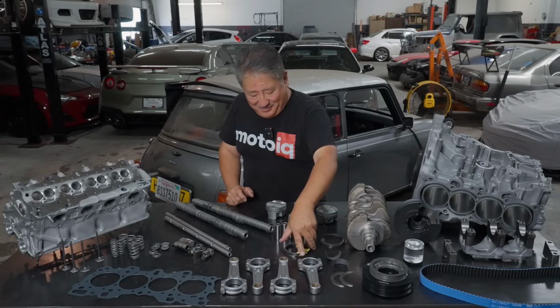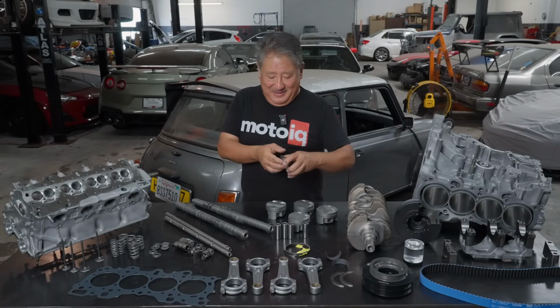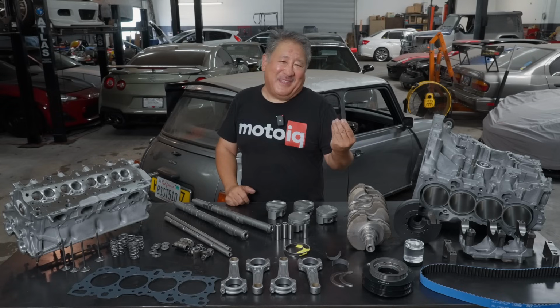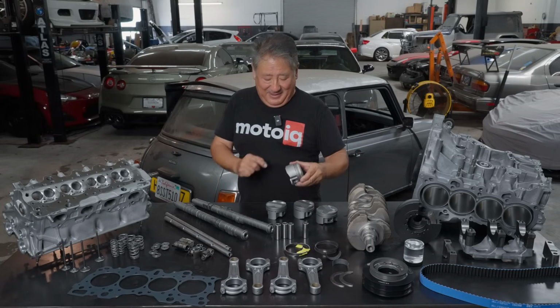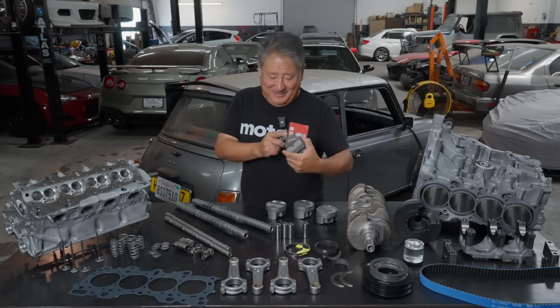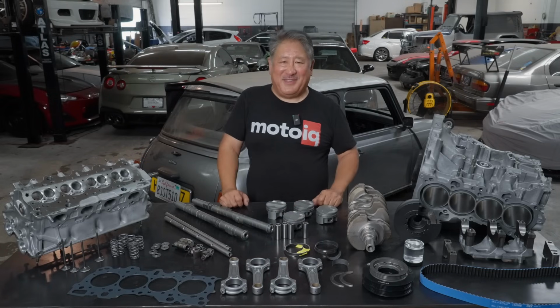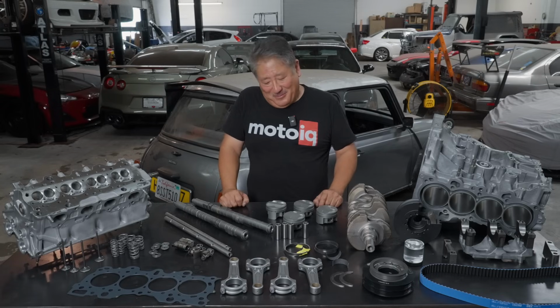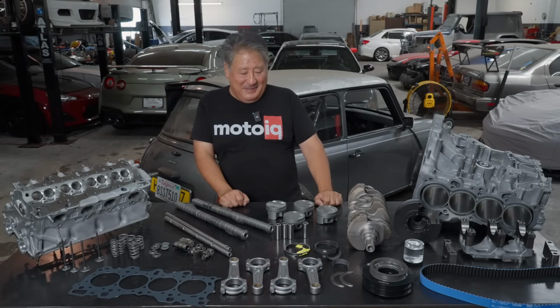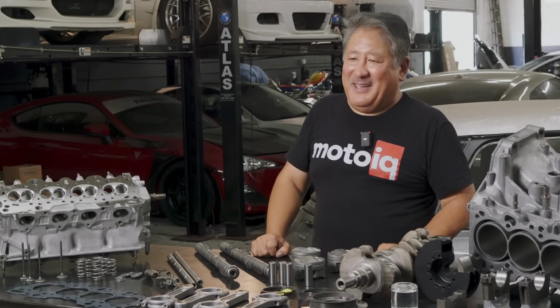Also, that little thin edge on the softer iron ring beds in quicker and wears into the cylinder wall faster, so you get quicker initial seal on startup. That doesn't mean the ring doesn't last long, but it works better in that application. The oil rings are narrow, low tension. They have a generous amount of drain back holes on the pistons, so they'll be able to effectively scrape the oil off, and you won't get an oil burner if everything's clearanced correctly. We really like the JE piston and ring package.